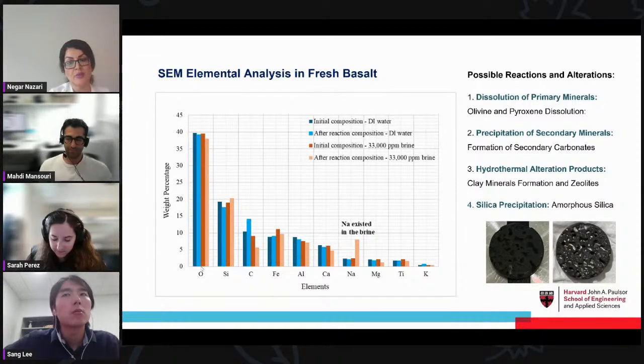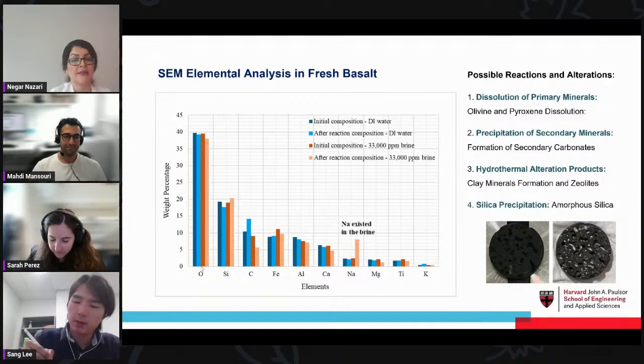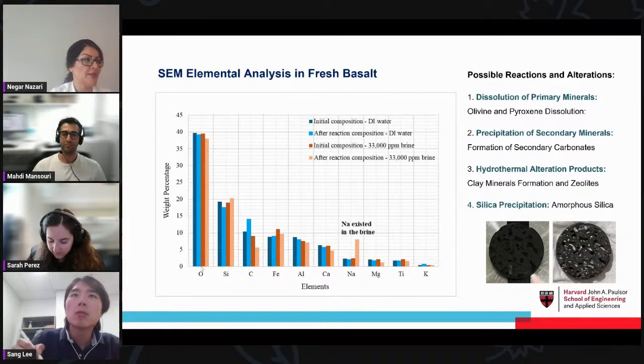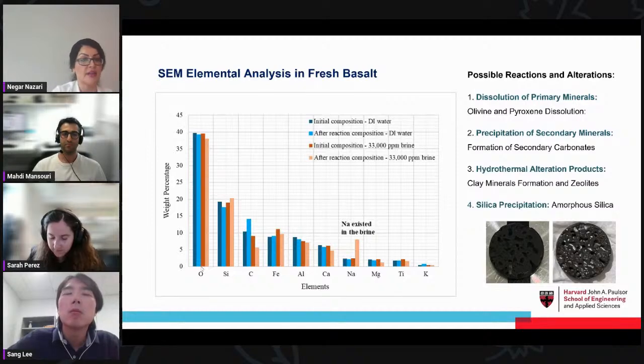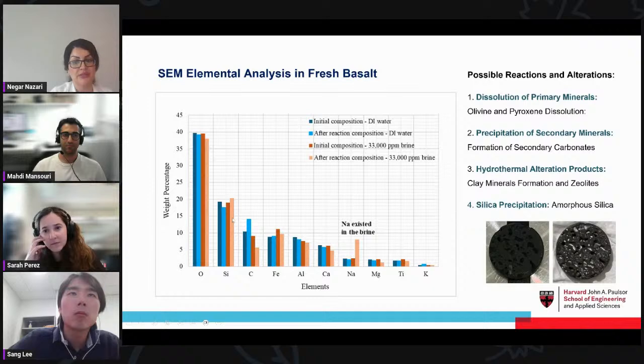We believe that we have the formation and the precipitation of secondary minerals that could be carbonates or any kind of silica precipitate. Another possibility was if it is clay or zeolite, but we cannot confirm if it's clay because we had a lot of silica and we see some silica precipitation in some spots in the left figure. We believe that can be some amorphous SiO2.